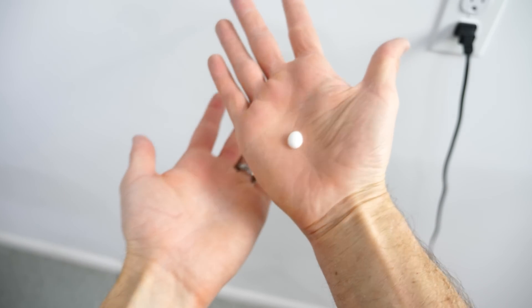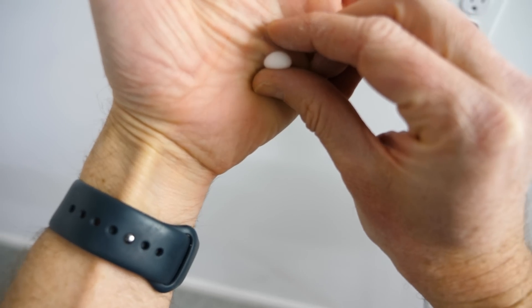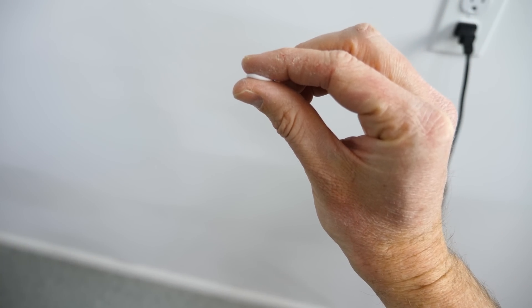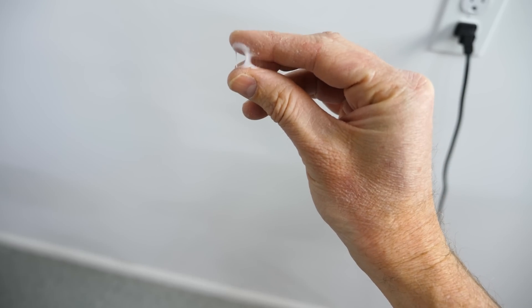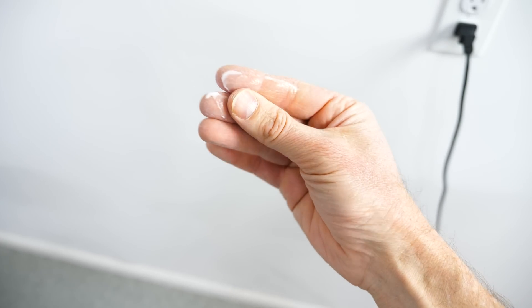And that's exactly what I've done here to make these pressure sensitive adhesive marbles. I took Elmer's glue drops and coated them with hydrophobic nanoparticles of fumed silica. This makes the outside of them hydrophobic so that they're no longer sticky, while the inside remains a sticky ball — but the inside can't be accessed until you squish the little beads hard enough to break the hydrophobic shell and release the sticky glue inside.